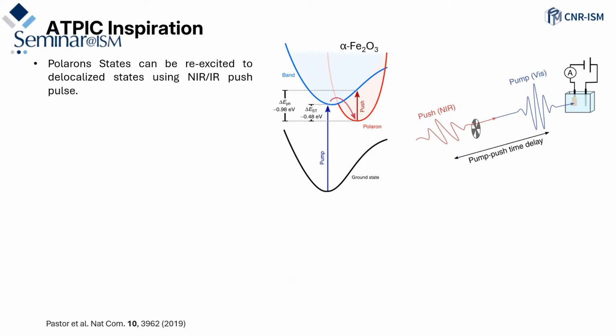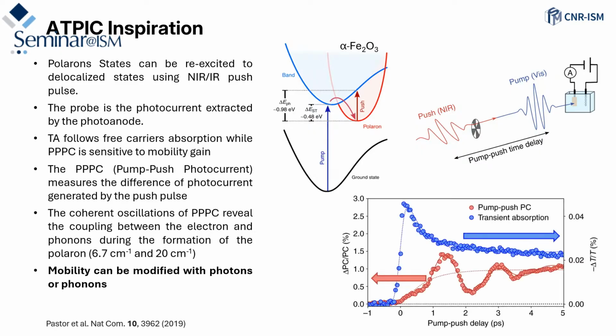Okay, so now the inspiration for the project. The inspiration came from another paper, from a group at Imperial College. What is very interesting here is that they make this experiment using two pulses, visible and infrared. One for exciting the system, and one for pushing the polaron again to the conduction band. And they just collect the photocurrent from this photoanode.